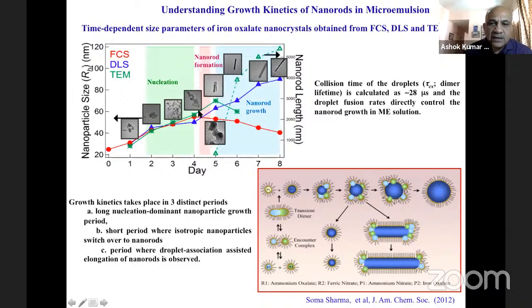But how do we know that it is going beyond a certain size? By looking at DLS data and electron microscopy of the particles which we get out of those droplets, which tell you that after a certain size the particles tend to agglomerate in a direction and then form the rods. So this is how we understand the mechanism of formation of the nanorods in this system.